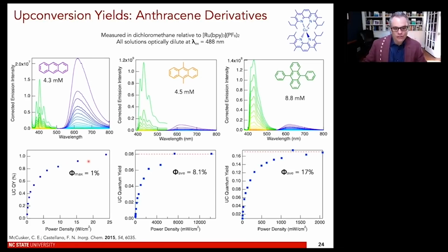What you get is when you get to the linear regime, the power density is effectively increasing, and power density basically gives you a limit to the yield that you can observe. And that's just well-established kind of stuff. But with copper, we can get to 17% with diphenylanthracene, which is much better than we ever could get with ruthenium-2. So it just shows you that even these subtle things, like changing sensitizers, really have an impact on the types of photochemical upconversion efficiencies you can realize.